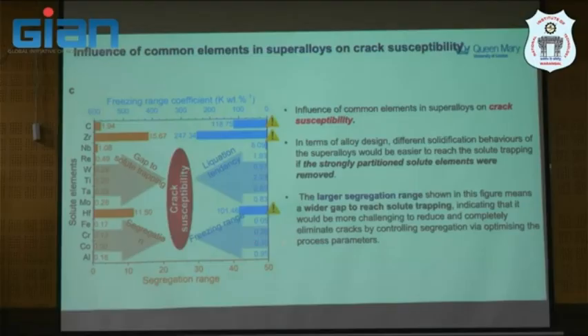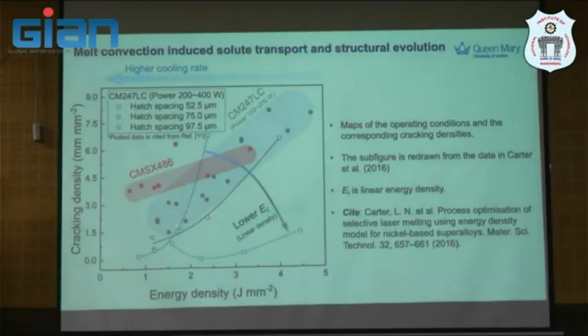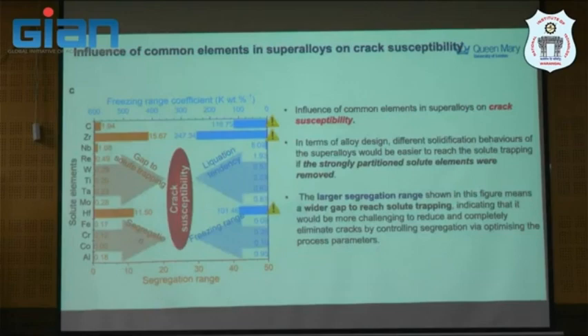Not sure. Or people are trying to see the role of carbon as well. And the larger segregation length means the wider gap of solute trapping you will get. That means hafnium, which you have a lot of in the CM247, will be detrimental to the crack susceptibility. Sometimes it would be more challenging to reduce and completely eliminate cracks, but it's about control and optimizing process parameters as shown before, which may help, but not a lot. It's about what is the acceptable range of the crack, but probably we cannot compromise with cracks, right? In a flying component, it's probably not possible.